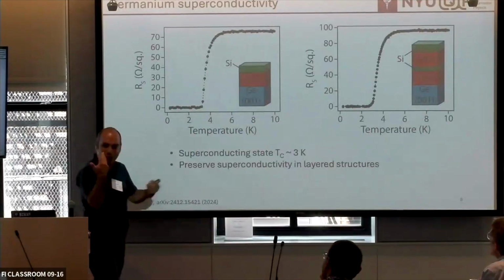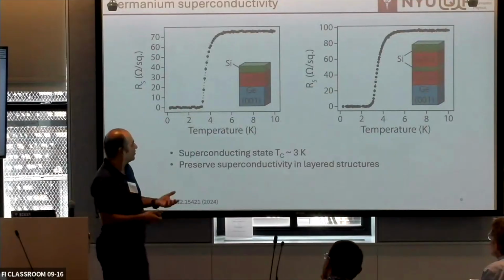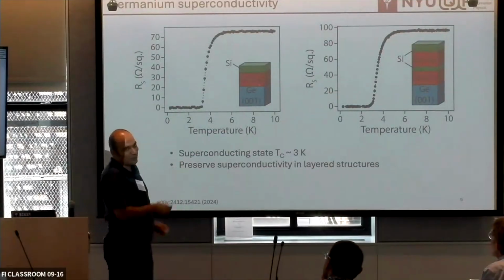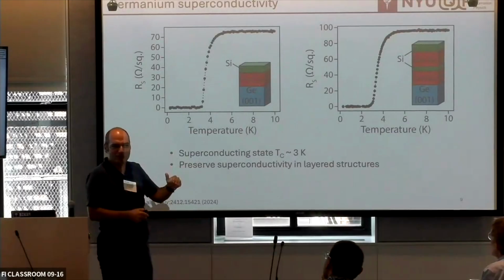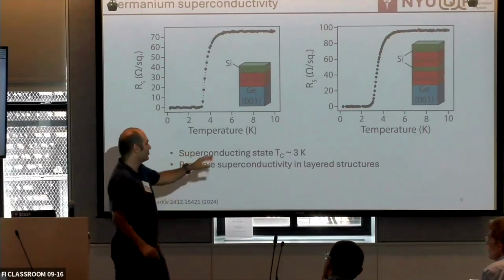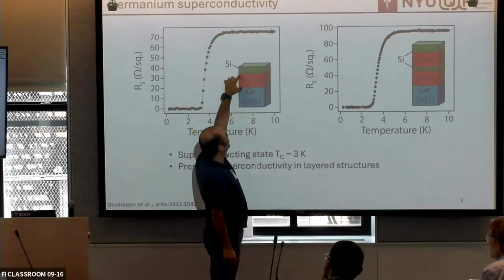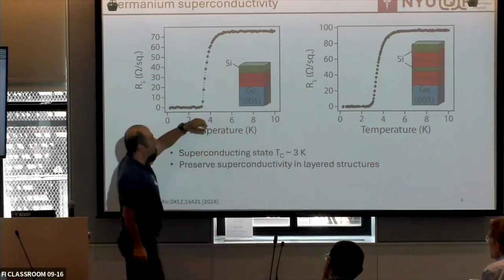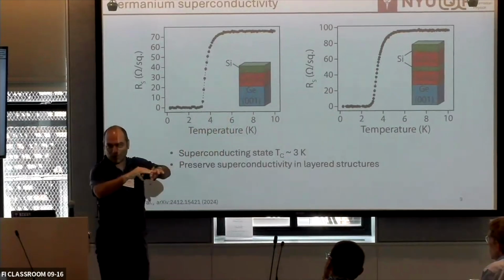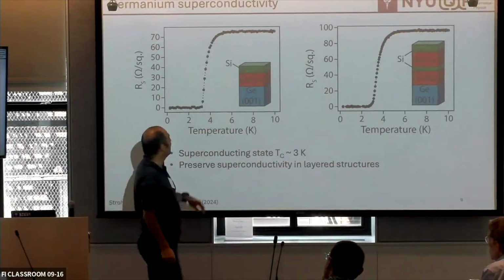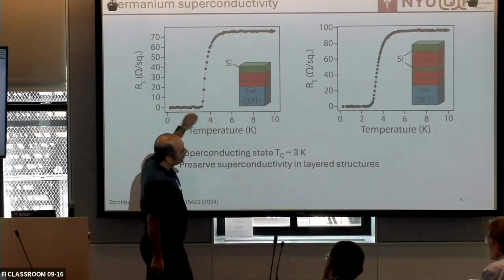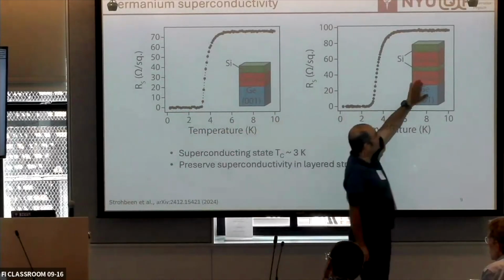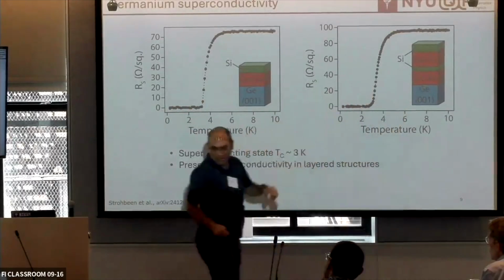So we said, let's grow more of this type that we are thinking we are replacing. Maybe we shouldn't put the silicon in the middle. Just grow something doped germanium. Just gallium-doped germanium, cap it, because germanium oxide dissolves in water, and the humidity affects it. Superconducting. Yeah, the structure I told you, superconducting.